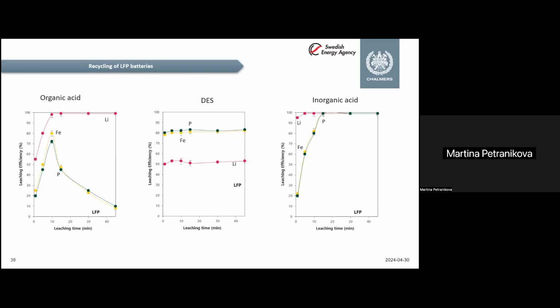With the deep eutectic solvent, the separation or selectivity wasn't that good, but we are still working on this research. And when it comes to inorganic acid, what is quite interesting is that these elements have different kinetics. If the leaching process is very short, we can get the majority of the lithium very quickly, while the iron and phosphorus stay in the solid phase.